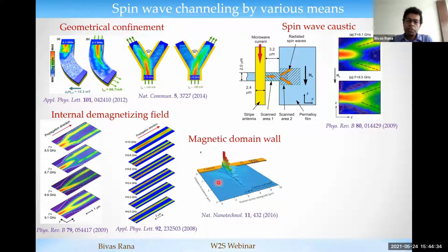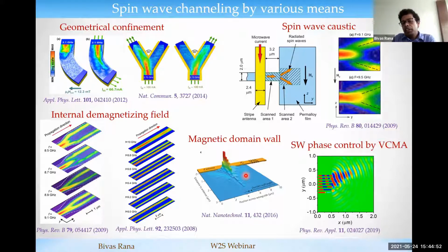The fourth method is confining the spin wave in the domain wall, because the domain wall creates some kind of potential well where you can confine the spin wave, and the domain wall size essentially can be reduced down to a few tens of nanometers. Another interesting way is to control the phase of the spin wave by voltage controlled magnetic anisotropy. Basically, you have several sources of the spin wave. Okay, then you selectively tune the phase of the spin wave by applying voltage controlled magnetic anisotropy, and then you interfere the spin waves, and from the interference, it goes in a selected direction. So if you want to change the direction, you just tune the anisotropy systematically.